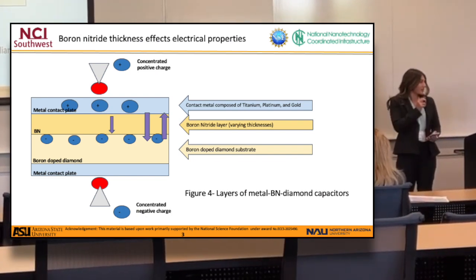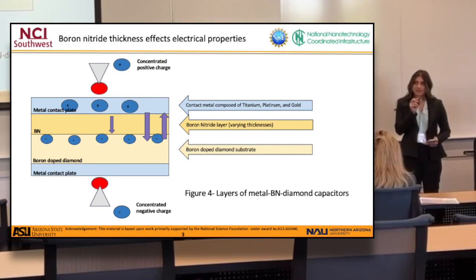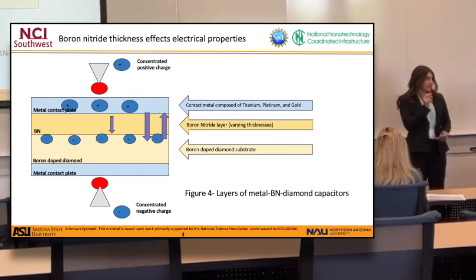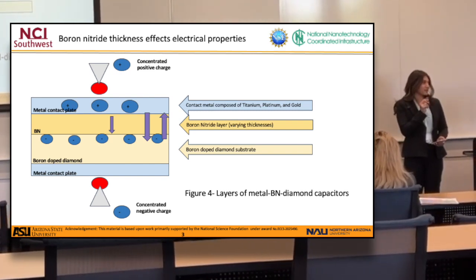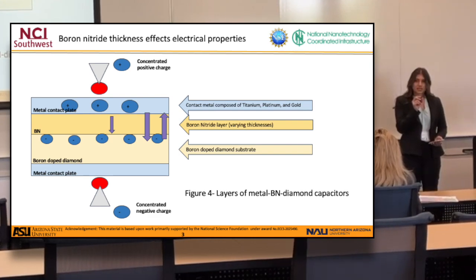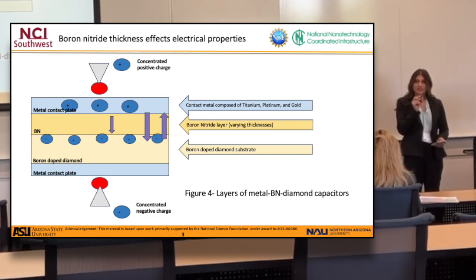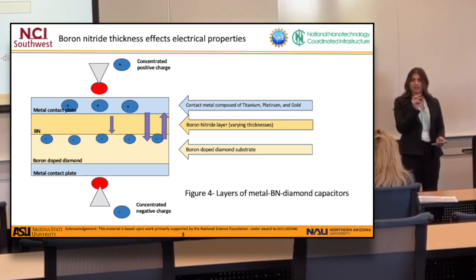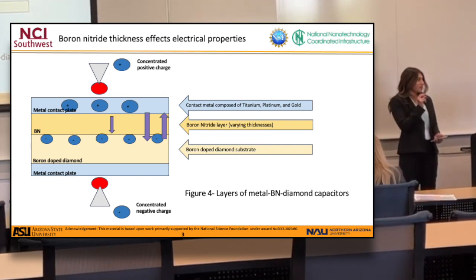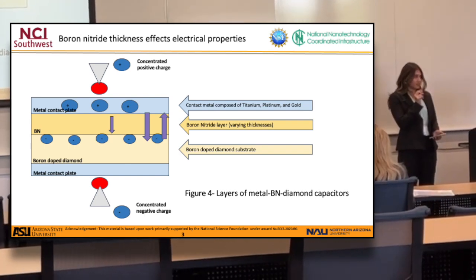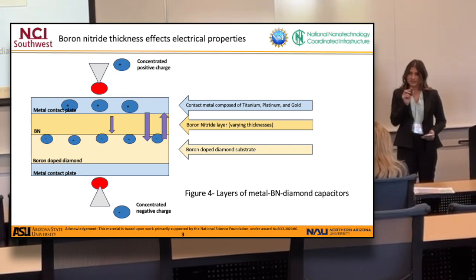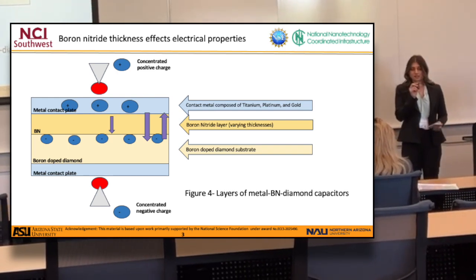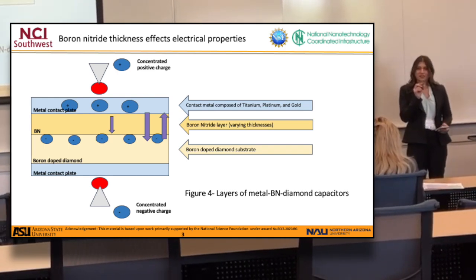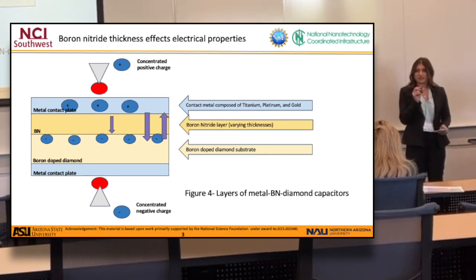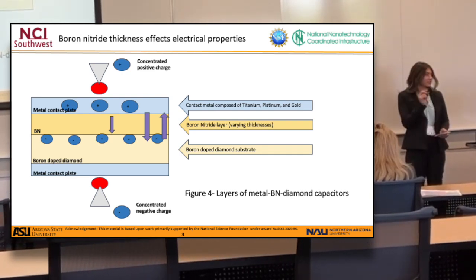So this graphic shows the different layers of the metal boron nitride diamond capacitors. Our first layer is the contact metal composed of titanium, platinum, and gold, and we actually fabricated this in the clean room. And then our next layer is the boron nitride layer, which has varying thicknesses within the experiment, but I specifically tested on 50 nanometer thickness.